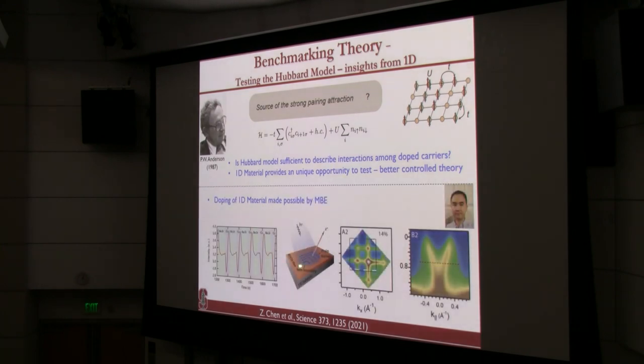But this, it turns out experimentally, has been very hard. In other words, the single crystals which we need for our experiment cannot be doped. Eventually, we were able to dope them with thin films. For example, this is a 14% doped MBE-grown film, and you can see it's a twinned crystal, so you see two sets of domains, each one-dimensional.